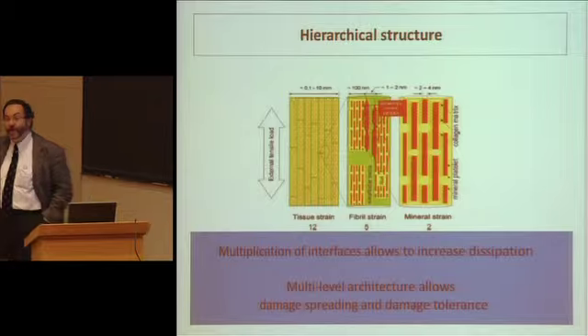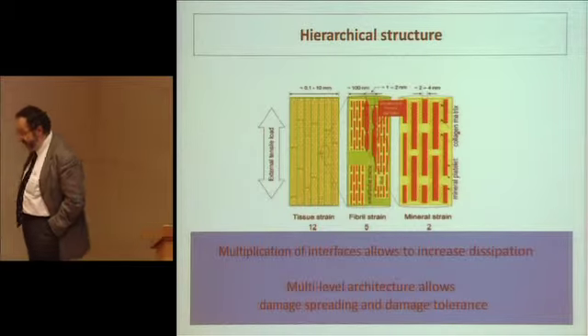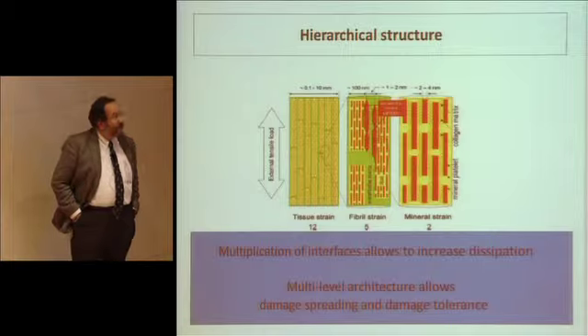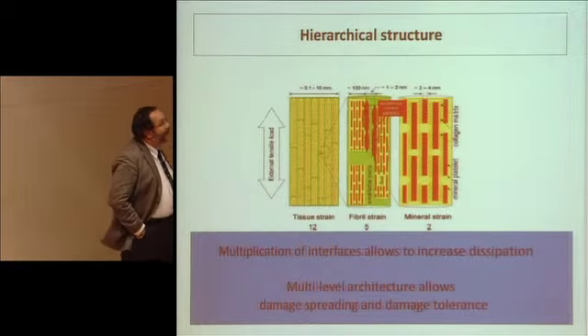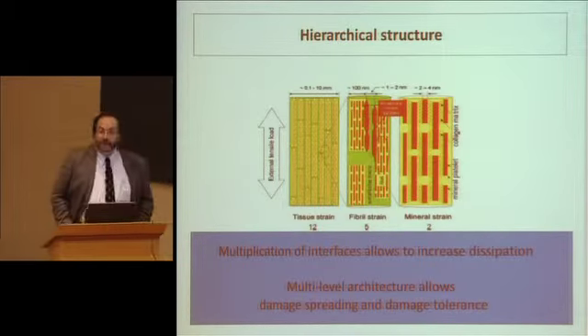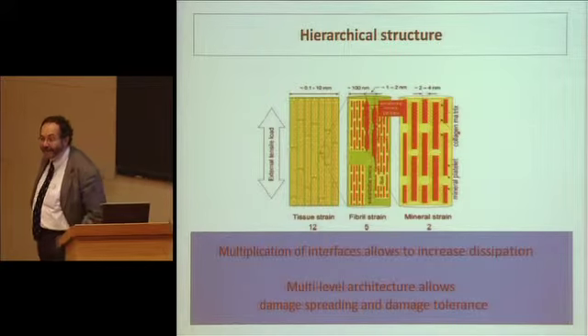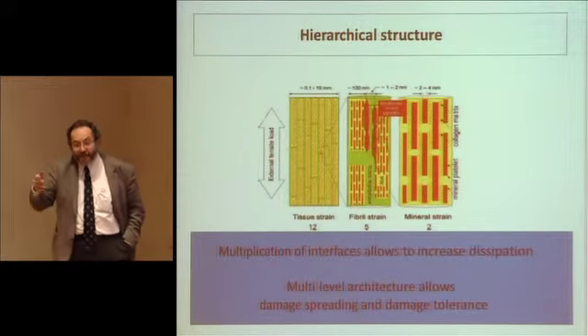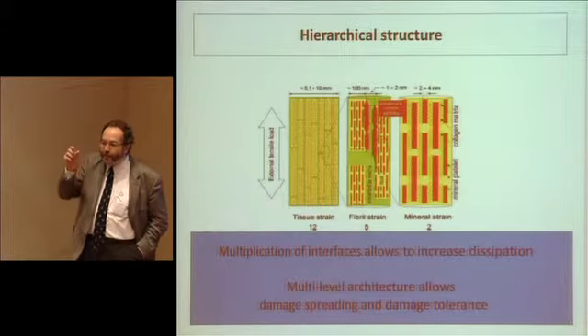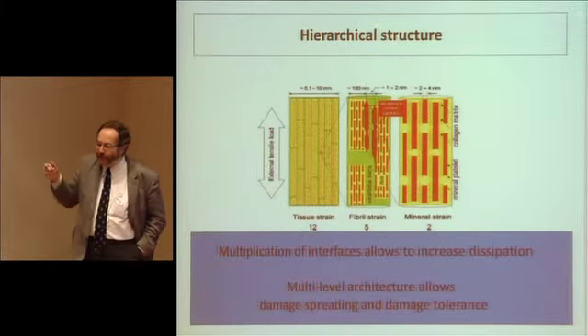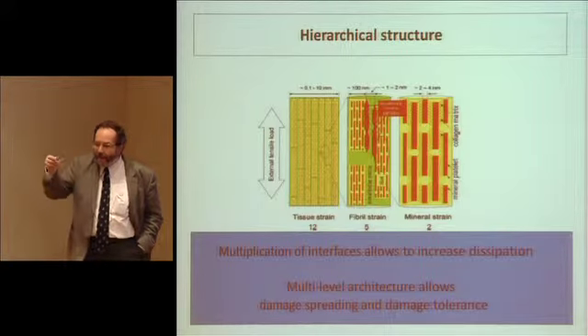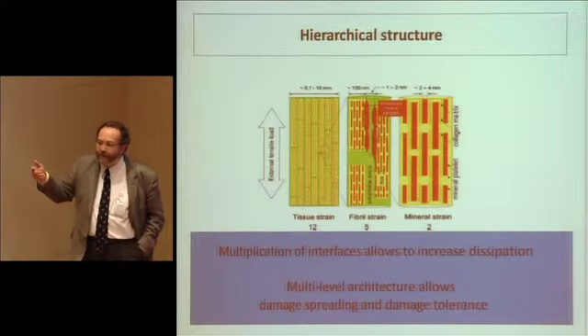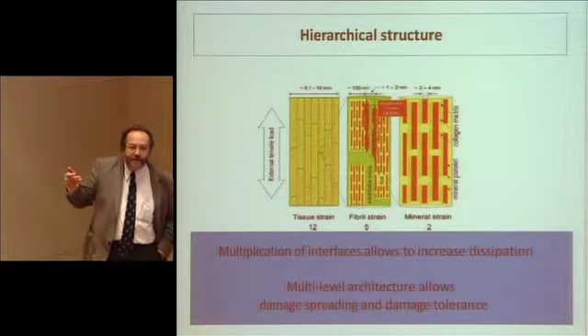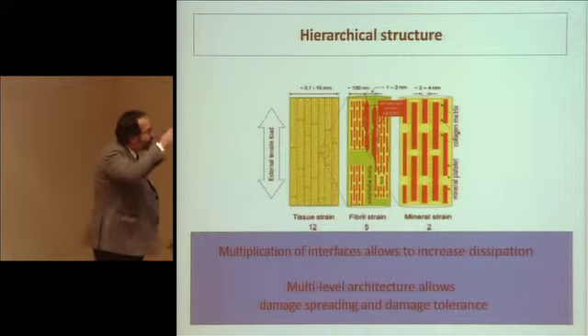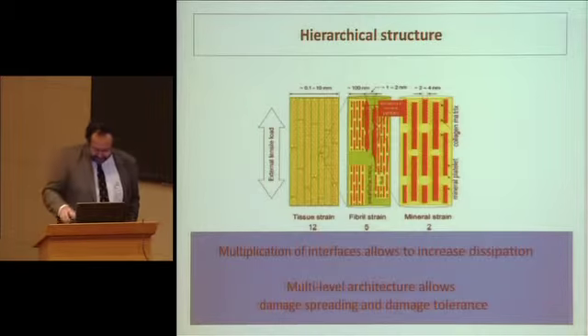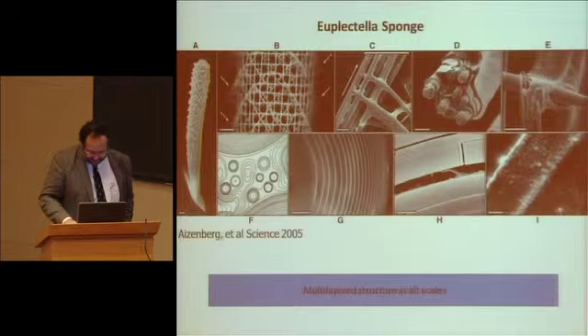So once you've done that, you have another scale. I've only talked about one type of architecture, one scale. Here I actually can't really go into very much detail, but the basic idea here is that when you're making a composite of a composite of a composite of a composite, when you have a whole hierarchy of architectures, you end up in a situation where cracks are always subcritical versus the scale above it. So the crack will propagate very, very slowly, allowing you to have damage tolerance that's particularly effective. These are ideas that have been very much developed by Gao.